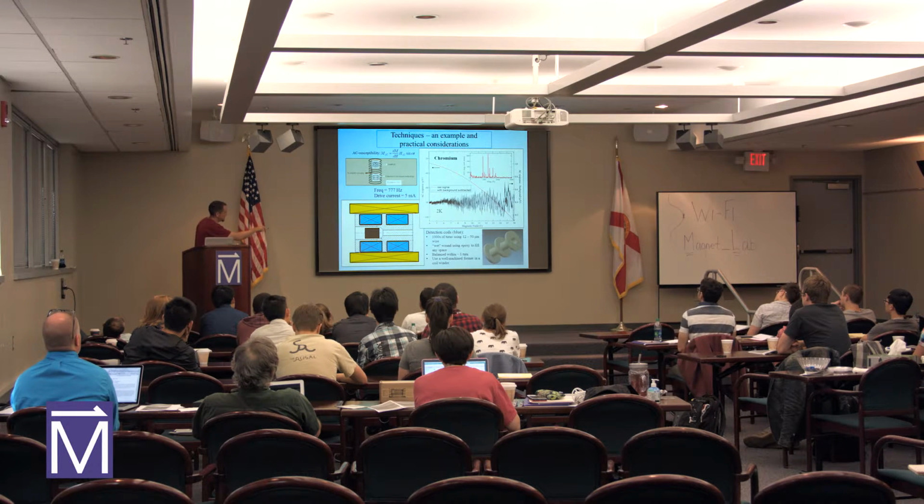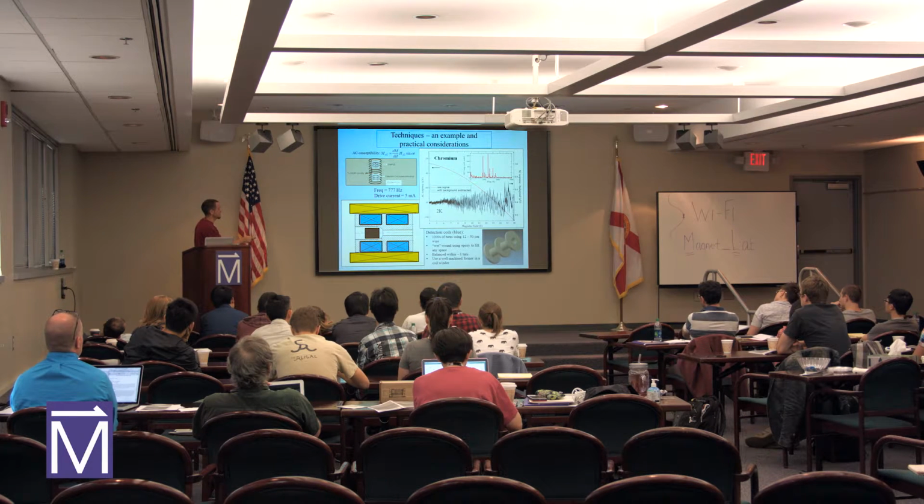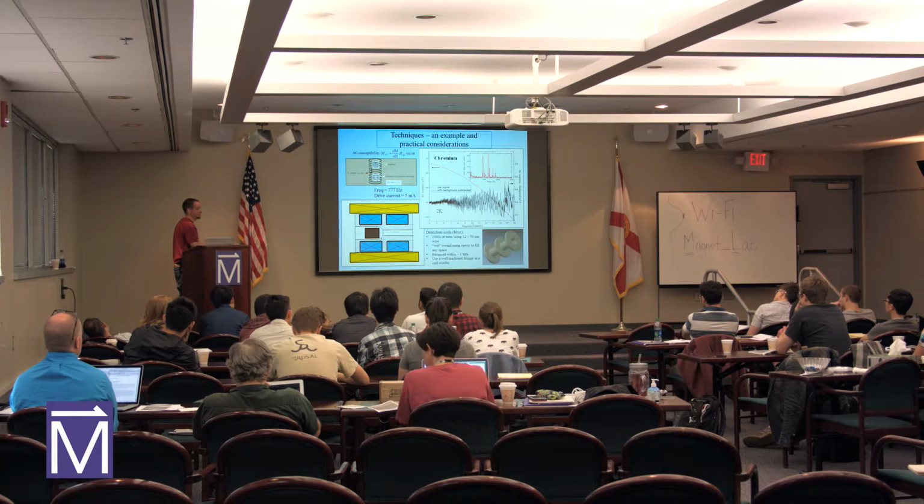It doesn't look very exciting here on the red line, but we have to do a background subtraction to see anything happen. And actually, the interesting changes are at the tens of nanovolt level. These oscillations come from taking, I think, a third-order polynomial from the background. And if we take a fast Fourier transform of this data, we see a bunch of distinct peaks here. So it can be difficult to make these different techniques work, but the payoff is that they can be really sensitive.